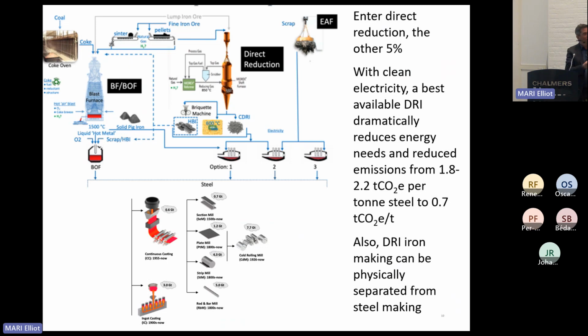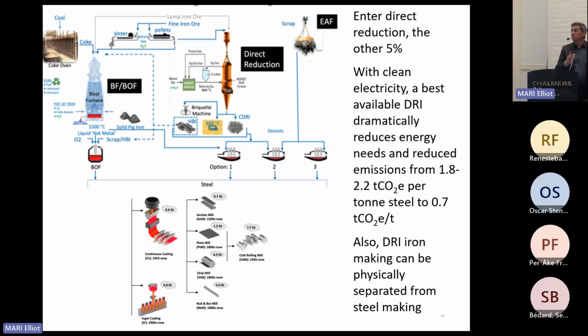You pre-treat the iron ore into these little pellets. With the DRI reactor, you run a syngas of hydrogen and carbon monoxide through the reactor. The carbon monoxide provides heat to drive the reaction. The hydrogen takes away most of the oxygen, and the monoxide becomes dioxide. What comes out of the bottom is a solid sponge iron, about 4 to 5% carbon. That then goes into an electric arc furnace, and you do your steelmaking there.